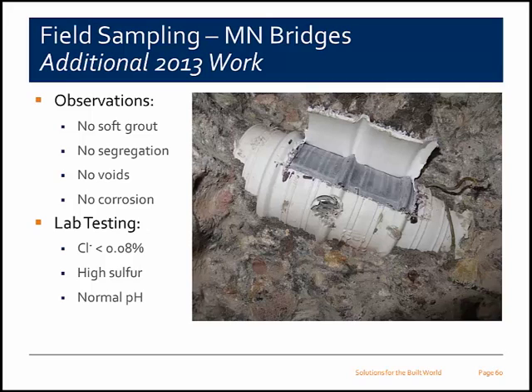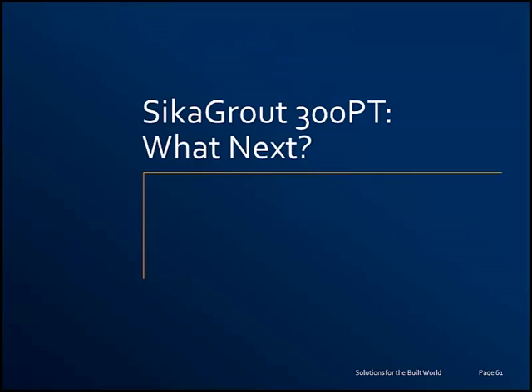And we tested the grout. We opened up and looked at 4 of the 16 tendons, and we borescope inspected the other 12. They all looked good. At the 4 that we opened up, we collected some grout for sampling. It all had low chloride content. There was a little bit higher sulfate content than normal or than expected, but not alarmingly high, and it was a normal pH. So that summarizes the field work and the lab work, but what's next?